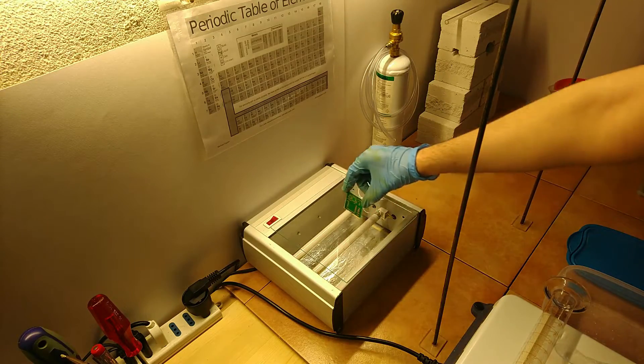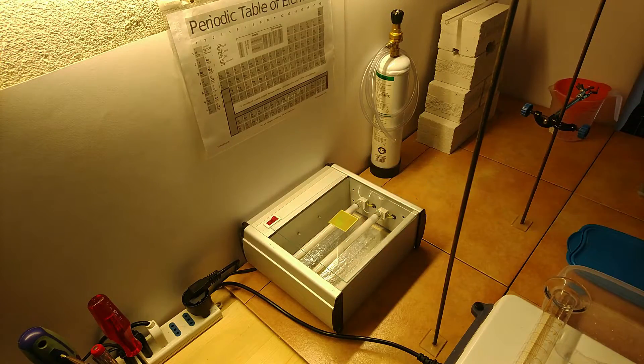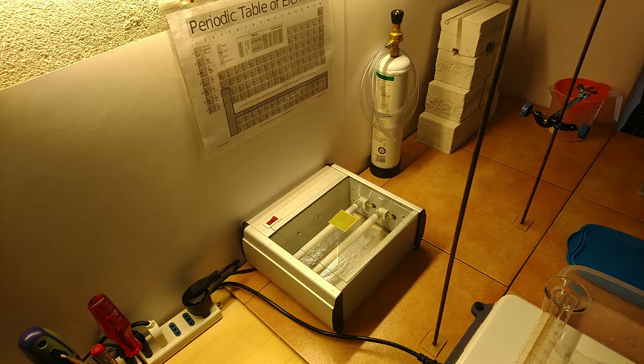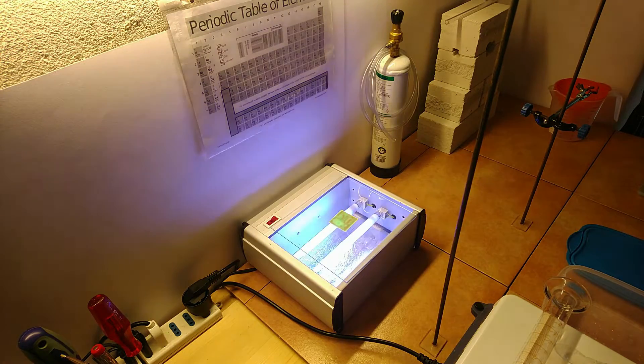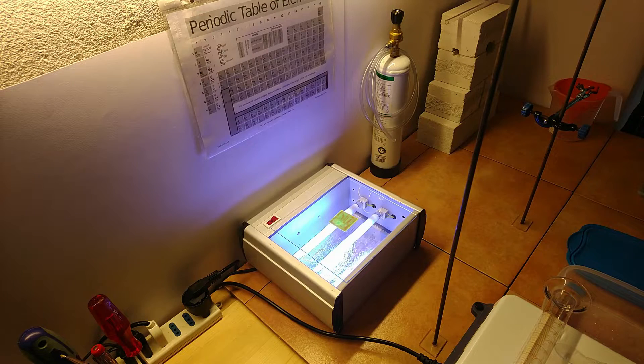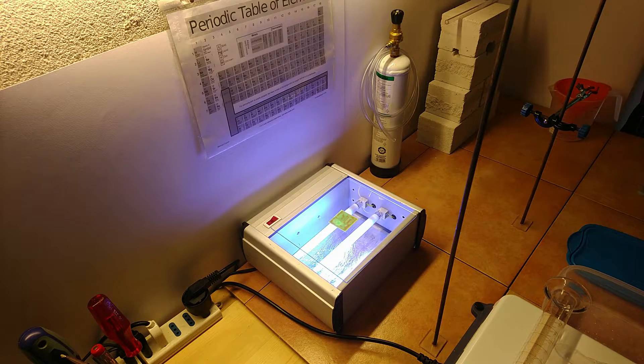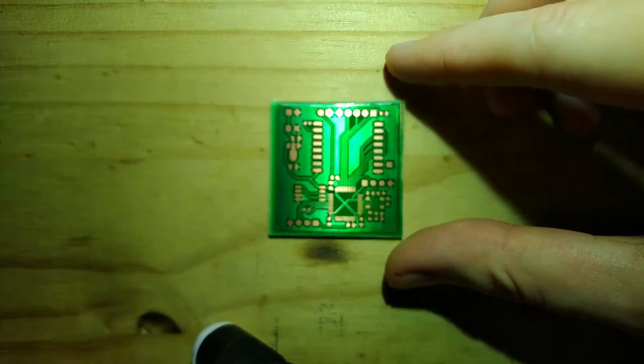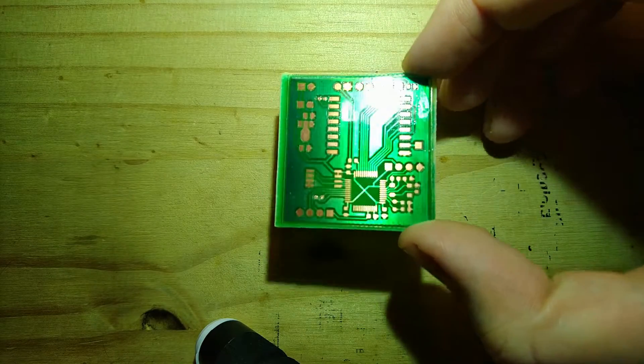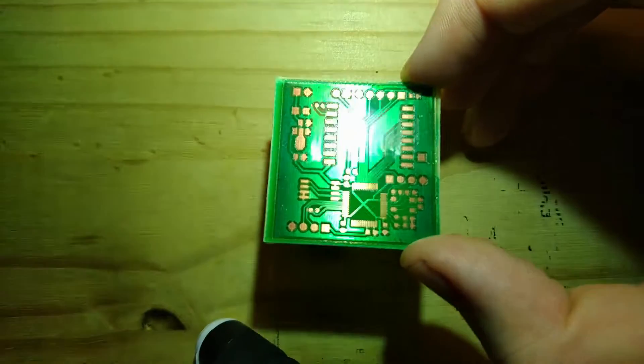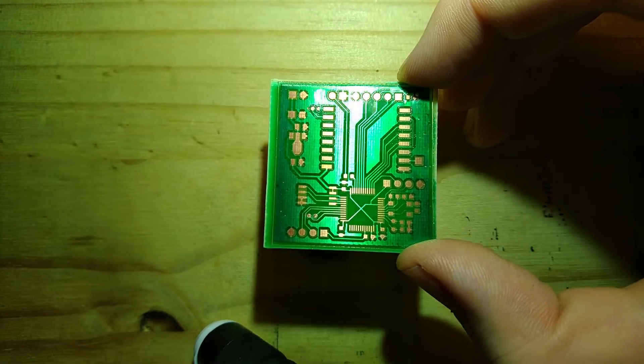After another water wash, it is best to expose the PCB without a mask to the UV light for half an hour to be sure the photoresist is fully polymerized. The PCB now has all the traces and a protective solder mask, but most PCBs also need holes, so drilling is needed.